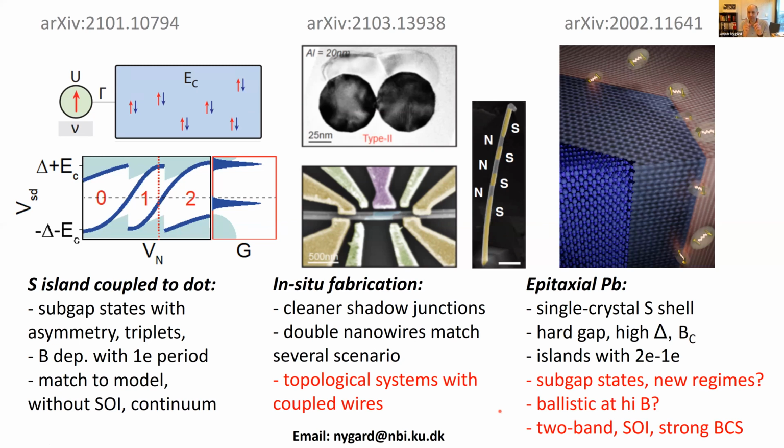So they're grown pretty close together in that case. They're also long and rather thin, so they're flexible. And at some point during the growth, I cannot say exactly when, due to vibrations at high temperature, they touch and stick. So that's plainly van der Waals attraction. And then they remain stuck in that configuration also during the metal evaporation.